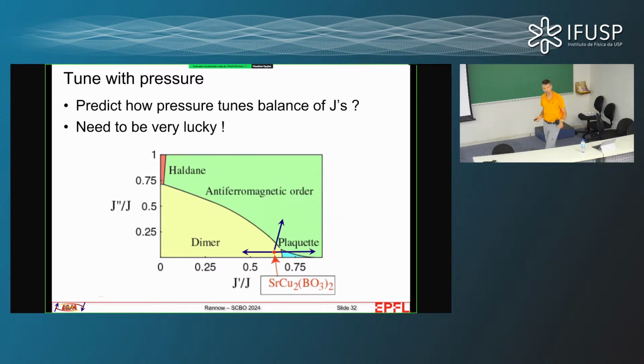Okay. So that was what happens to this system if you just increase temperature. Now, one could also hope to change the ratio of the two couplings in the system. In fact, there's a theoretical prediction that if you change this ratio, you could also add some interaction between these two-dimensional layers. Then you would have a phase diagram roughly like this one, where if you just increase coupling between the layers, you might be able to induce antiferromagnetic ordering, similar to if you had no diagonal coupling at all. But if you were able to increase this J prime, you might get to an interesting intermediate state here. And if we look at the couplings that we have in strontium copper borate, it looks like we're really close to this new quantum mechanical phase that people had predicted. Actually, there were about 5 or 8 different predictions for what really happens here, but everyone agreed that something is happening.